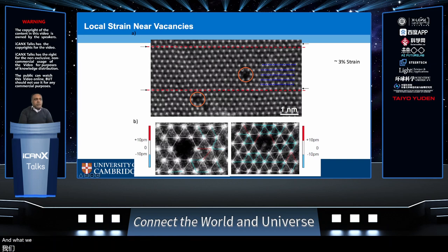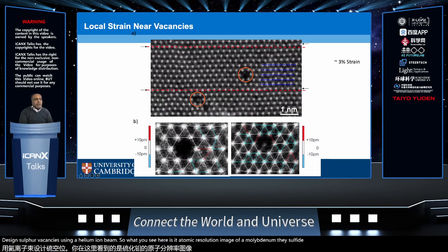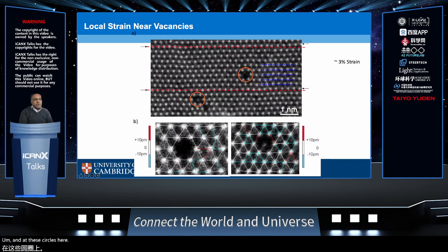And what we found is that these were rationally designed sulfur vacancies using a helium ion beam. So what you're seeing here is an atomic resolution image of molybdenum disulfide. These orange circles show where there's a sulfur atom that's been missing. If you tune the concentration of sulfur vacancies using a helium ion beam, then you can achieve the right concentration to increase the activity of the MoS2.